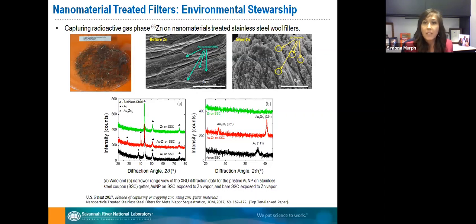If you have stainless steel wool, it doesn't capture this zinc 65 plume. And we decided, hey, let's put some gold nanoparticles. They are smaller, they are more reactive, and we can try to actually capture this zinc 65 plume. And of course, there are many other requirements. You cannot just go with any material, because there are a lot of experimental conditions that stop us from using any type of material, due to the requirements of the plant. So what we found is that gold was capturing the zinc, and you can see on the right some of the deposits that capture this zinc.